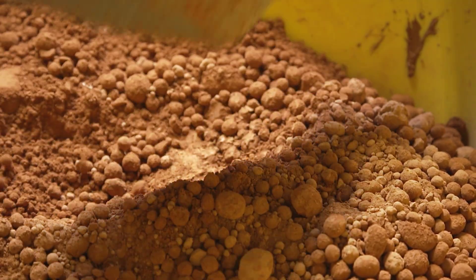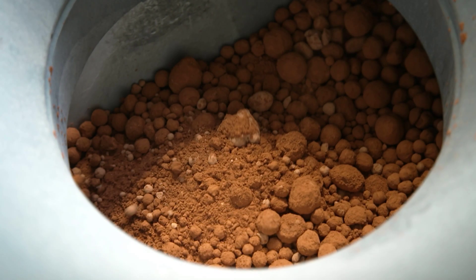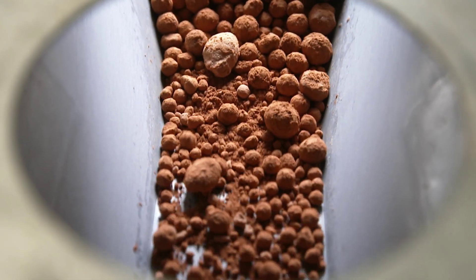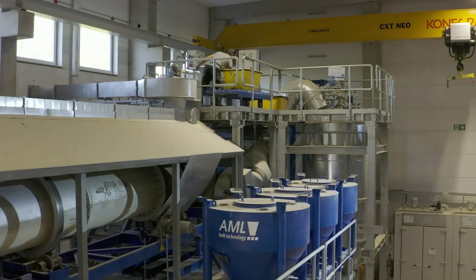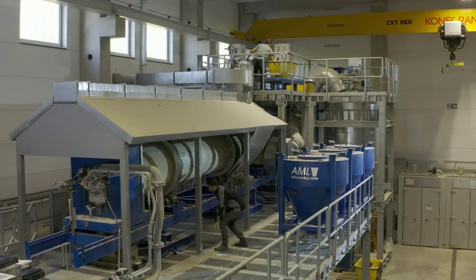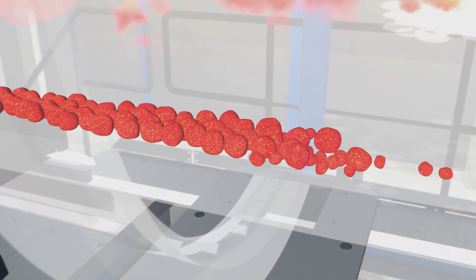The engineers in Weimar then feed the material into the final step of their recycling process. It falls through a shaft into a special rotary kiln that is six meters long. Inside, a gas flame heats the material to 1,200 degrees Celsius. Due to the slight incline and rotation in the furnace, the granules move towards the flame. A glass-like melt is formed at such an extremely high temperature. In this hot zone, the diameter of the beads doubles. They are porous and therefore permeated with air. In addition, the sulfur contained in the gypsum out-gases as sulfur trioxide.